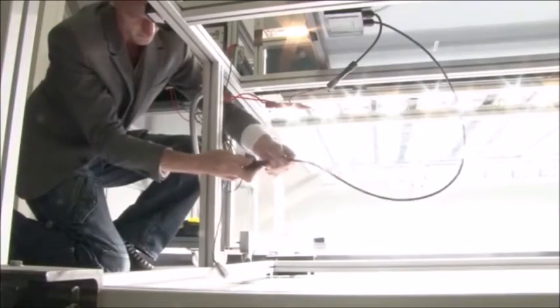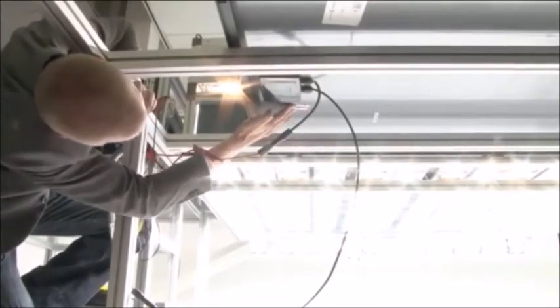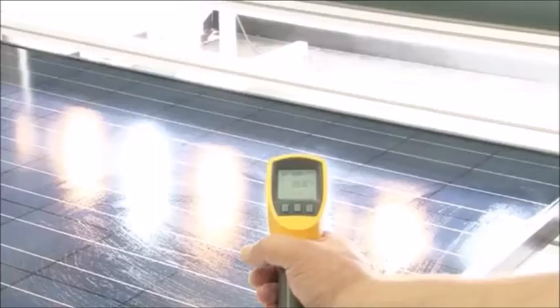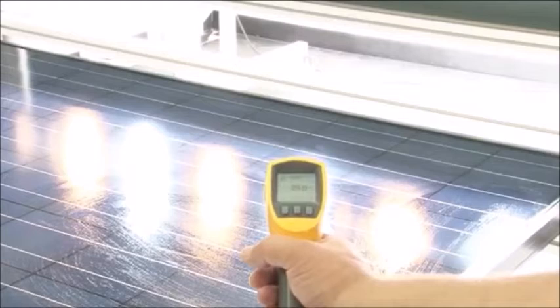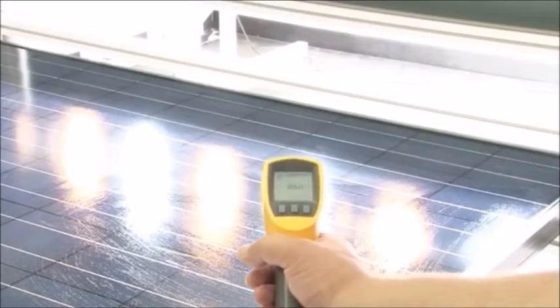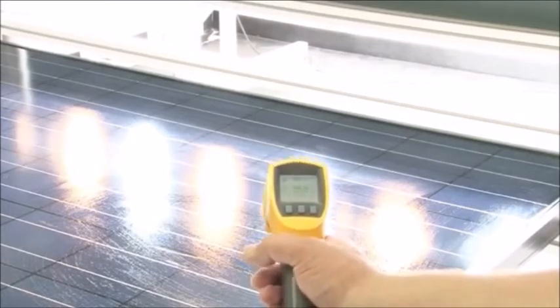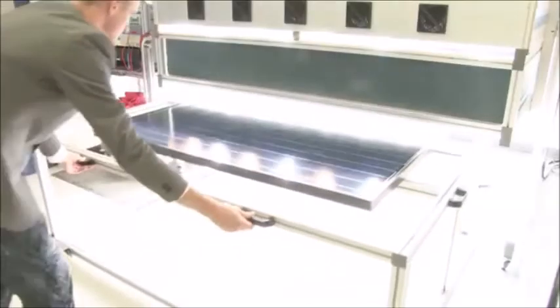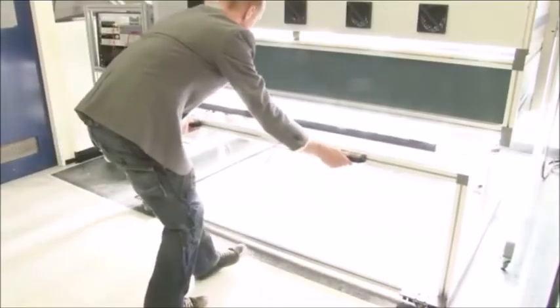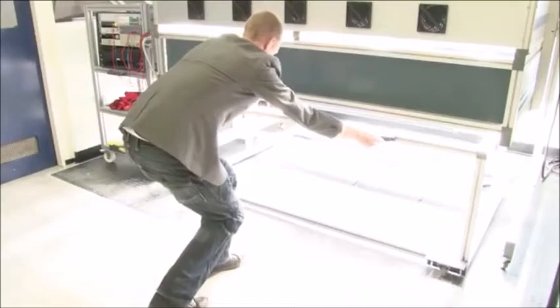The crystalline silicon solar panel needs to be connected to the voltage supply and the ampere meter. In addition, a thermocouple is connected to the panel to monitor the temperature of the panel during the JV measurements. Without additional temperature control, the solar panel will heat up in time. Here we demonstrate that the panel is at a required 25 degrees Celsius using a Fluke infrared thermometer before the panel is moved under the solar simulator.